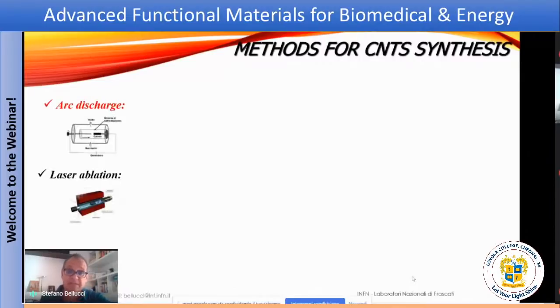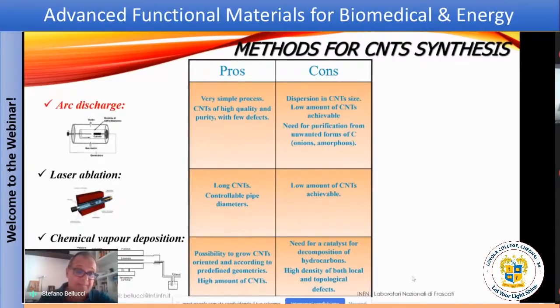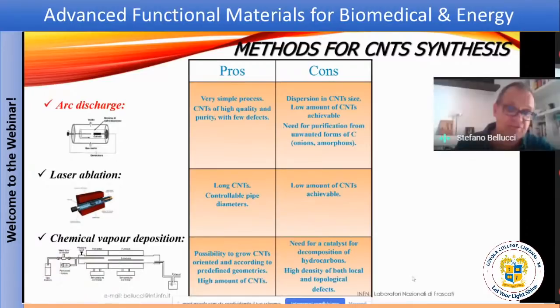So great properties, but how do we make them? We can make them by 3 methods: arc discharge, laser ablation, which are physical methods, or a chemical method, that is the deposition of chemical vapors. They have advantages and disadvantages. Typically, the chemical vapor deposition, which is the one that is used industrially, essentially has the drawback of producing nanotubes only when catalyst metals are included in the reaction, and so a lot of impurities are present in the final product and need to be removed.